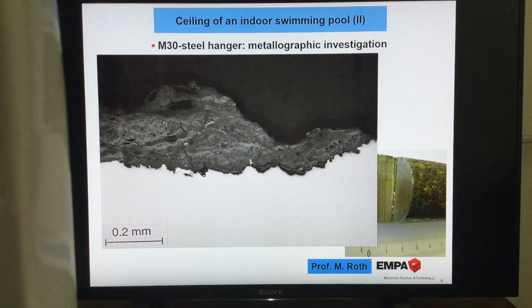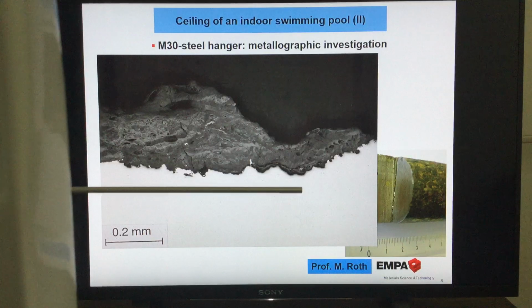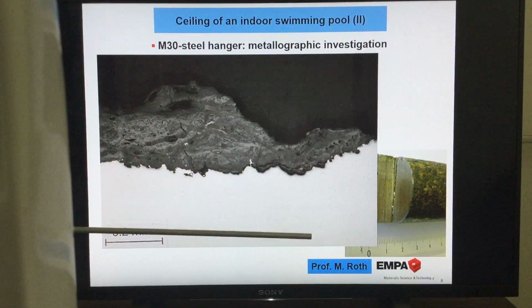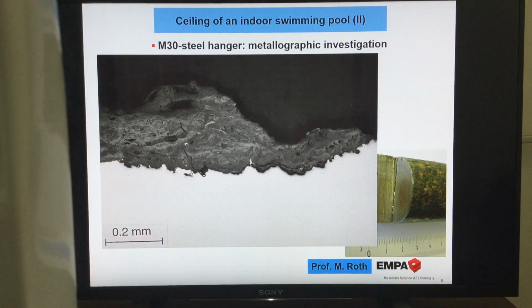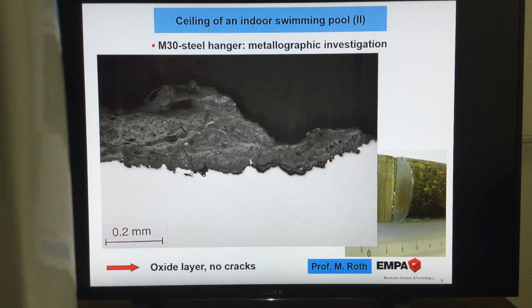We compare this again with the Uster case. We have here this corroded layer, but do you see any crack? There is no crack inside the material. To watch for cracks, it is also very important that the base material, the iron, is not etched. You can etch it, then you see the microstructure, but without etching you would see much better if there is any crack. You see here a small crack in the oxide layer. That is even the reason why it is a little bit bigger here. We will come back to this later. But important, no cracks inside. And the cracks, they are the dangerous part we have to take into account. Okay, now oxide layer, no cracks, keep in mind.